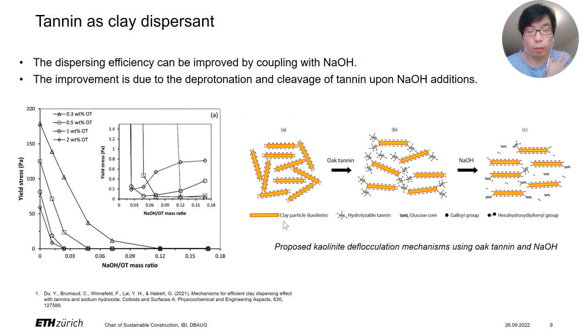Of course, with this information, we can think about some way to increase this dispersant efficiency. We can further add sodium hydroxide, because sodium hydroxide can deprotonate and disaggregate the tannin structure to make it more negatively charged, and we have a more abundant negative structure afterward.